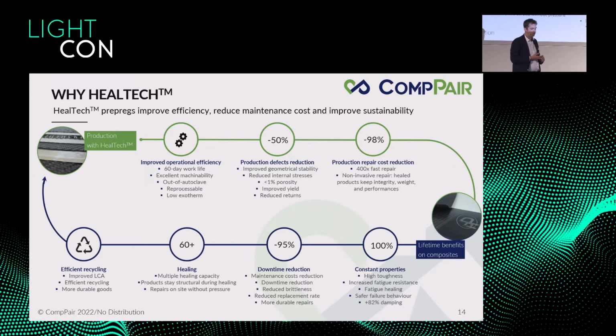They can be processed really nicely out of autoclave. And then because there is regeneration, because the cure cycle is at 140 degrees and we heal already before, out of the production, you can have for certain types of applications already reduced porosity and reduced internal stress, and I'm going to give an example right after as well.